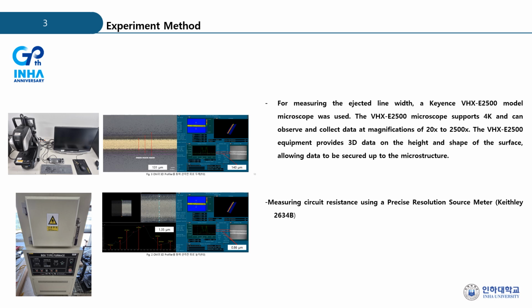A Keyence VHX-E2500 model microscope was used. The VHX-E2500 microscope supports 4K and can observe and collect data at a magnification of 20 to 2500 times. The VHX-E2500 equipment provides 3D data on the height and the shape of the surface, so that data can be secured up to the microstructure.